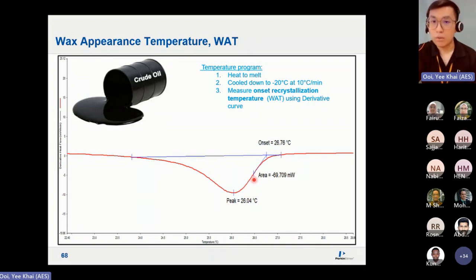We do not take the peak point, we measure the onset. That means for the crude oil transfer line, in order to prevent recrystallization inside the transfer tube, causing blockage and everything, we need to maintain the temperature higher than the onset temperature. For example, if this crude oil starts to crystallize at 26 or 27 degrees C, your transfer line must be higher than 27 to prevent the crude oil from recrystallizing inside the transfer line. This is the wax appearance temperature application.